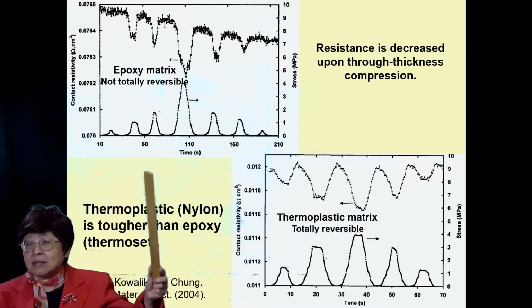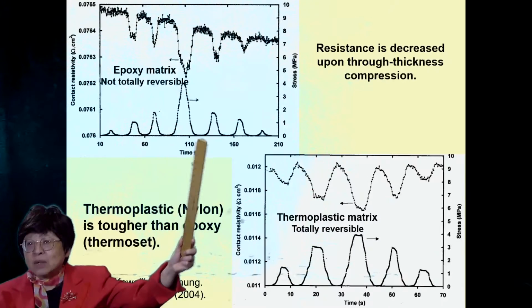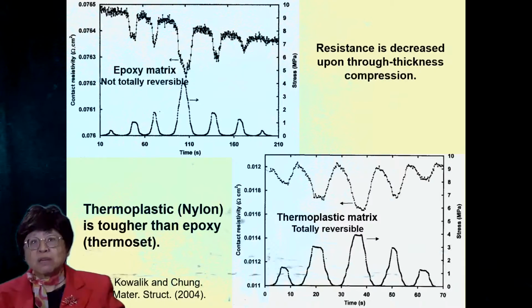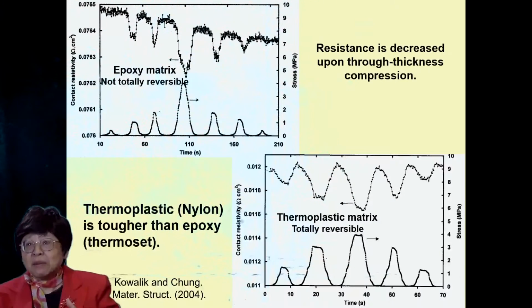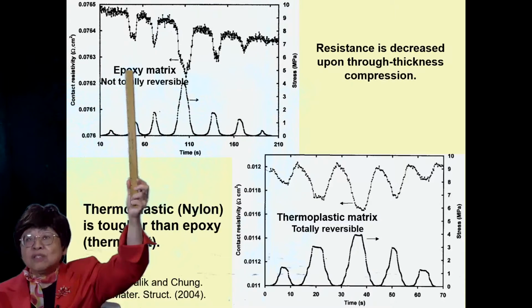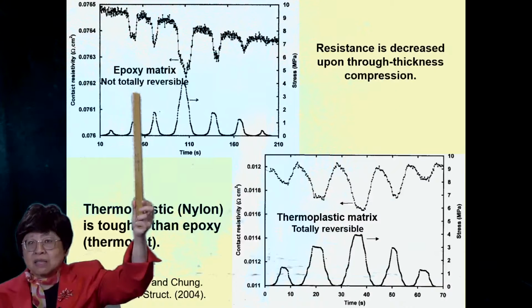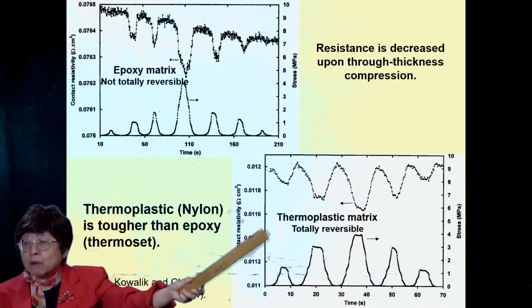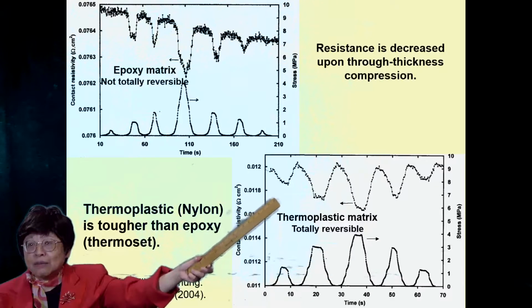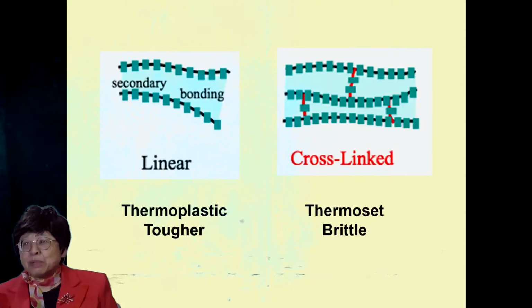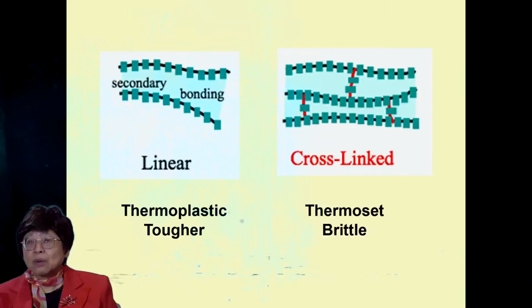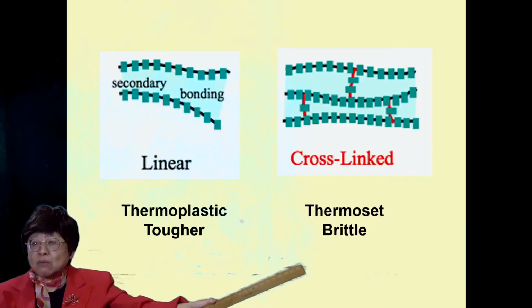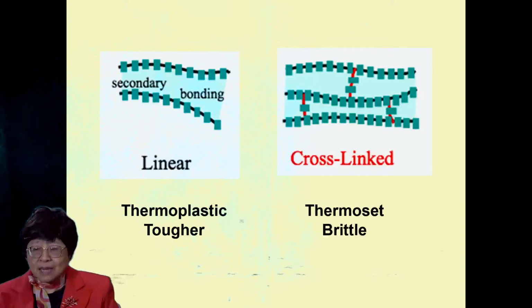Every time one compresses, and the compressive stress is shown in the curve below, the contact resistivity goes down because the squeezing increases the proximity between the plies. However, the resistance decrease is not totally reversible in the case of an epoxy matrix composite. However, for a thermoplastic matrix composite, it's totally reversible. And that is simply because the thermoplastic involves linear molecules, so it's tough relative to the epoxy, which is a thermoset and is brittle, involving cross-linking. So actually, it would be better off if one uses a thermoplastic matrix in place of the epoxy matrix.